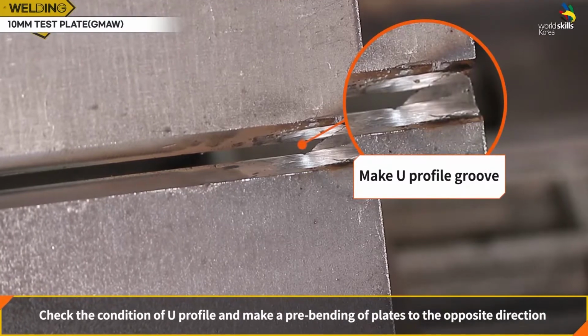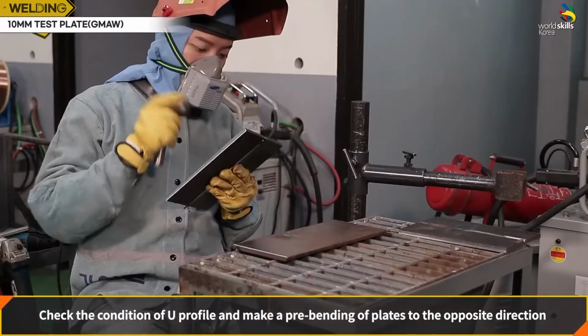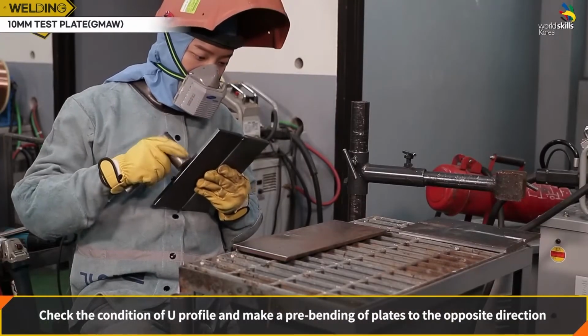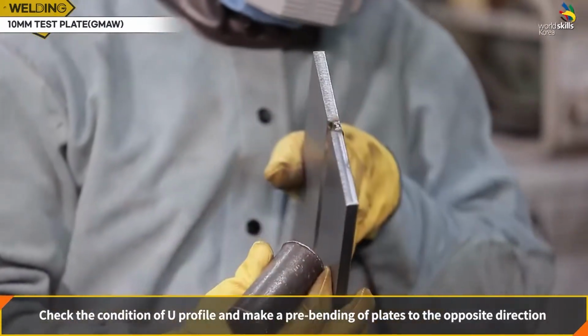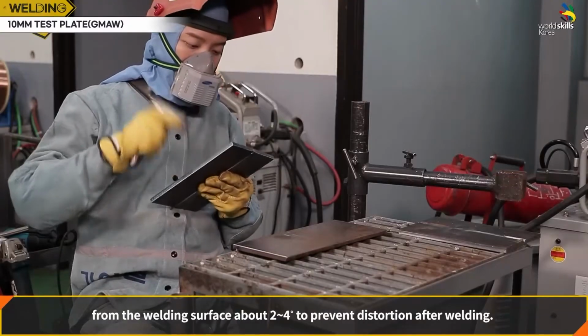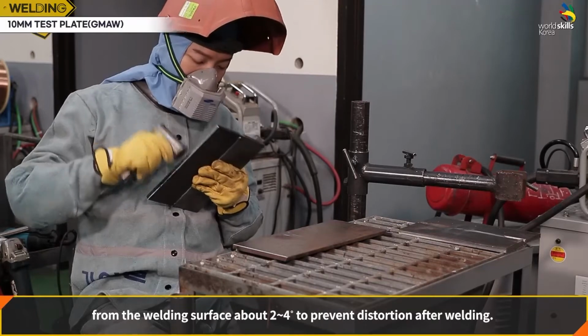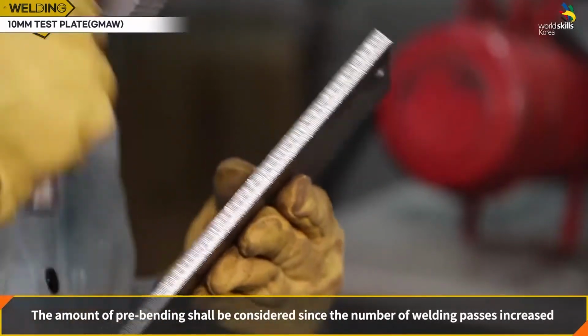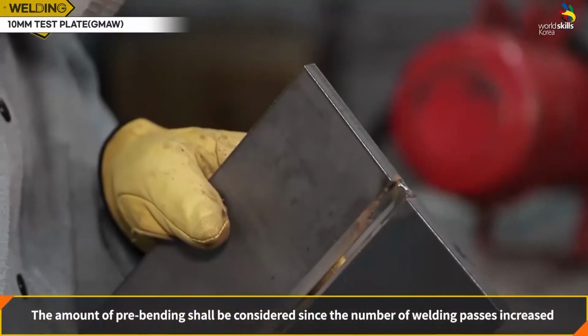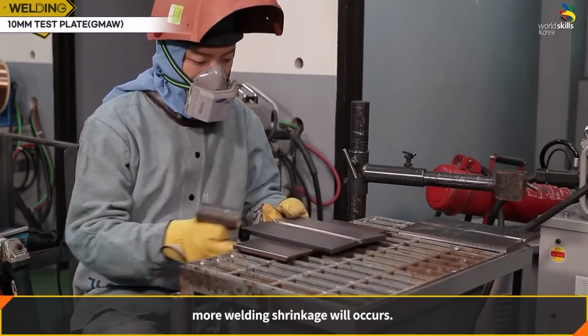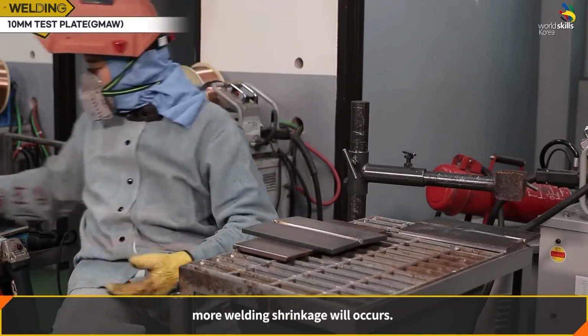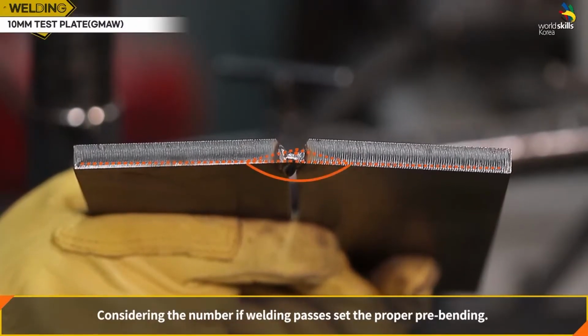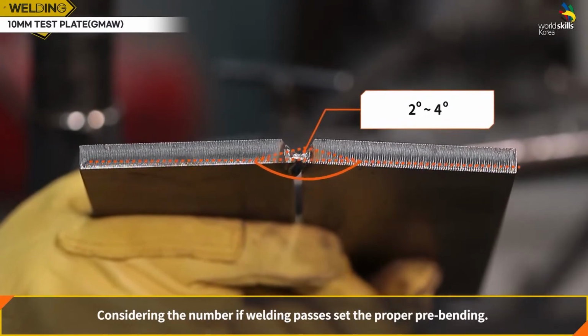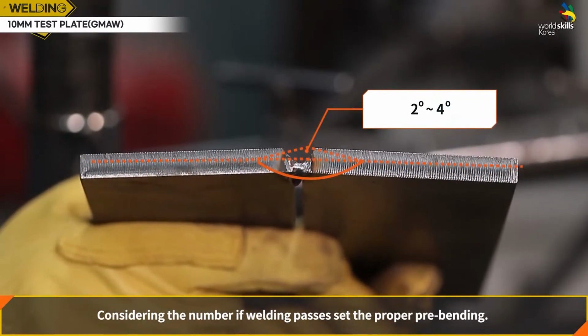Check the condition of the U-profile and make a pre-bending of the plates to the opposite direction from the welding surface, about 2 to 4 degrees, to prevent distortion after welding. The amount of pre-bending shall be considered since the number of welding passes increases, more welding shrinkage will occur. Considering the number of welding passes, set the proper pre-bending.